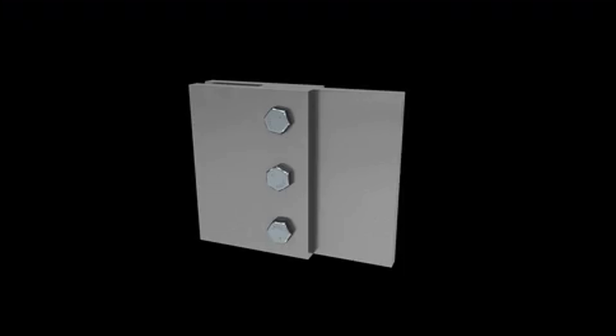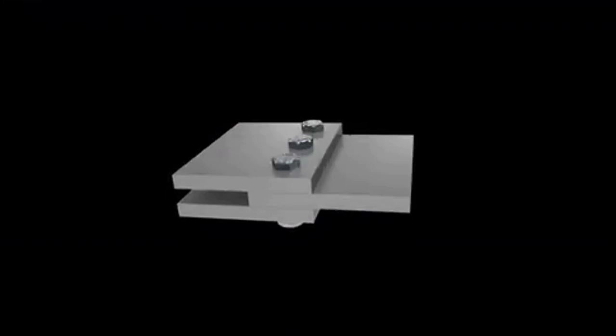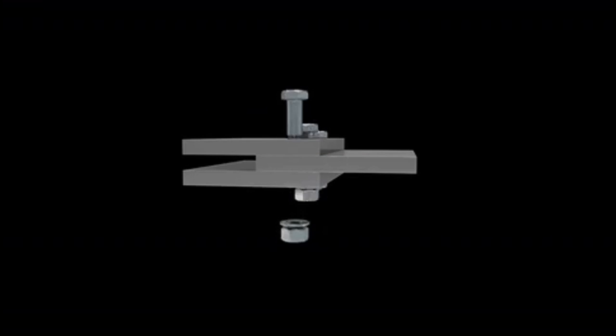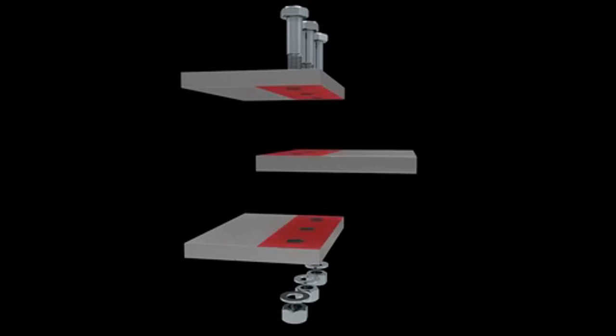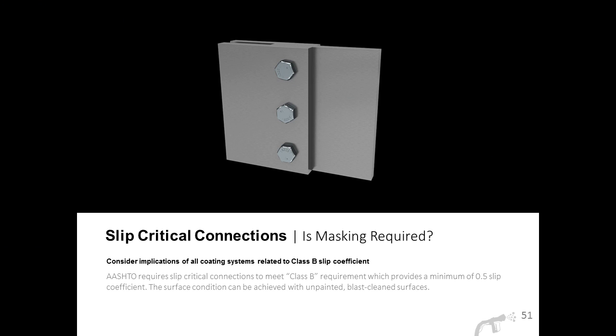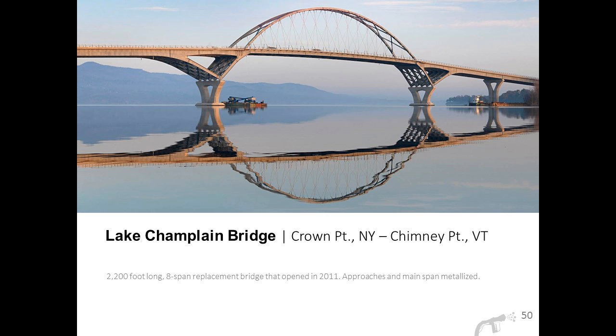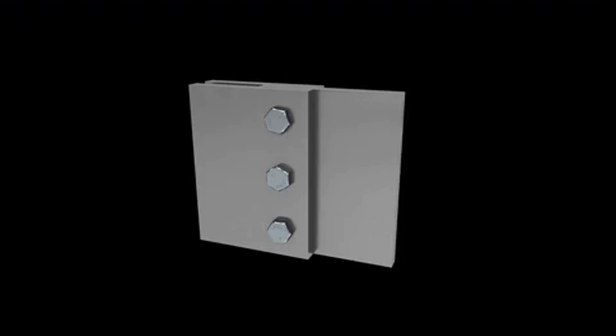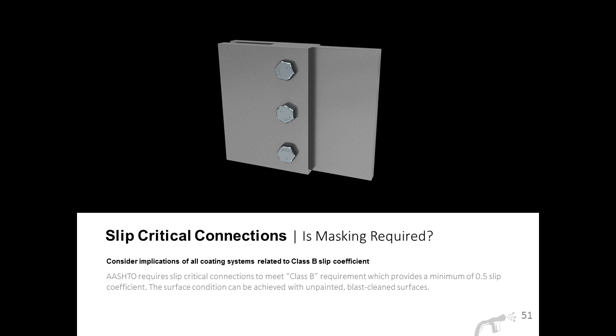So I'm going to play this video for you on slip critical connections as I go through this. Any additional coating over metallized surfaces has to meet a Class B requirement for slip critical connections, or you'll have to mask the connection, which drives up the cost. AASHTO requires the slip critical connection to meet Class B, which essentially provides a minimum of 0.5 slip coefficient. Typically, the engineer has to select a frictional slip coefficient between the layers of a connection to calculate the slip resistance. I'll go back to this as I go on.